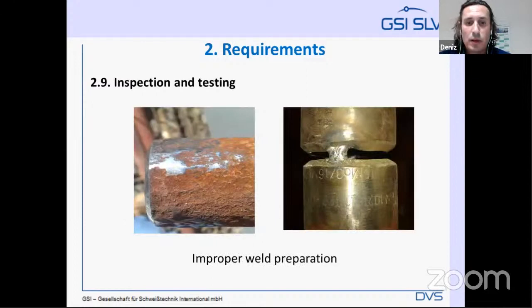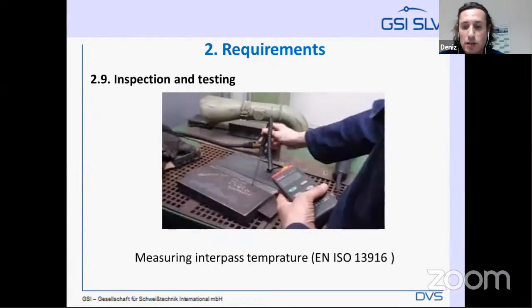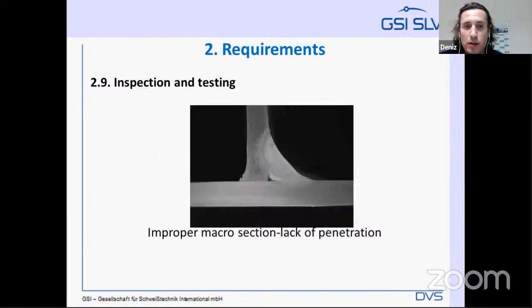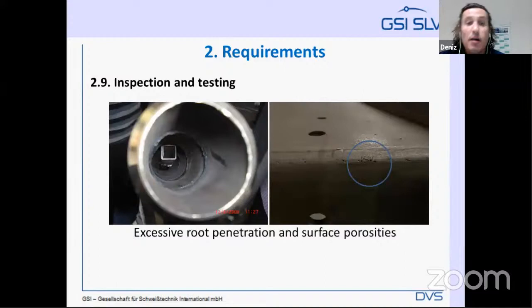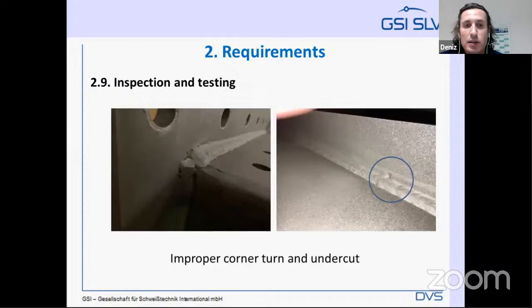A before control, for example, improper weld preparation: on the left side is a rusty material and on the right side is an improper groove, weld groove, too much gap, you can see, and a very bad angle. Also, you can see a during control, for example, measuring interpass temperature. Improper macro section, lack of penetration. These are after control. You can see excessive root penetration on the left side and surface porosities on the right side. Again, on the left side, there is an improper corner turn and also lack of fusion, and on the right side, there is an undercut.